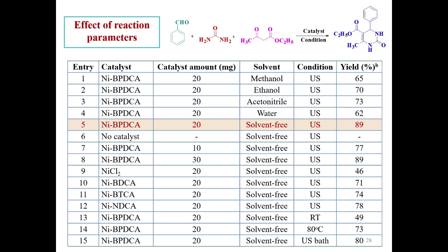Now, the effect of reaction parameters. When we conduct any organic reaction with the help of different catalysts, it is very important to understand the effect of the reaction parameter on the final yield of the product. And as mentioned, we have conducted this reaction in the presence of the catalyst by varying the amount of the catalyst in milligram, by changing the solvent or under solvent-free condition, in different conditions, in the presence of the ultrasound cavitation technique, or at rising temperature, or even in an ultrasonic bath.